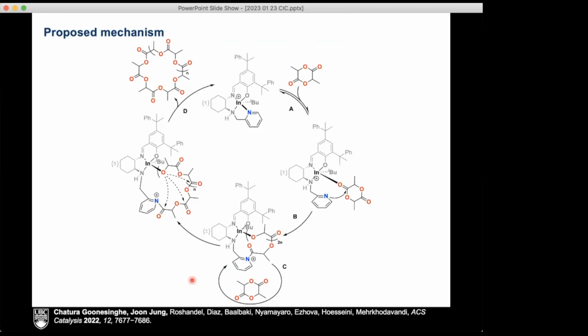So the slowest part, and the part that takes a long time, a lot of energy, is this addition of the lactide, actually displacing the pyridine. Takes a lot. Once the lactide is coordinated, the pyridine can attack. It's not a very good nucleophile, but it is known that pyridine itself can polymerize lactide. Not very well, but it does. But as soon as you have this very first attack and formation of this alkoxide, the alkoxide is a very good catalyst for lactide polymerization. And under the reaction conditions, which is 100 degrees Celsius, this is going to take off, right?